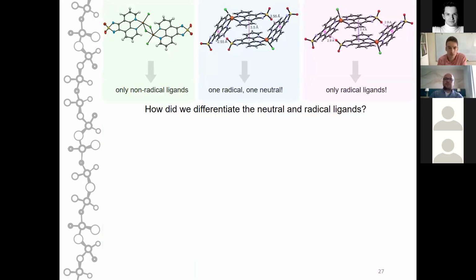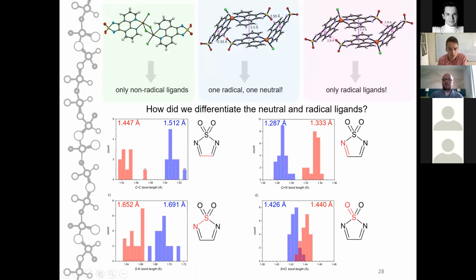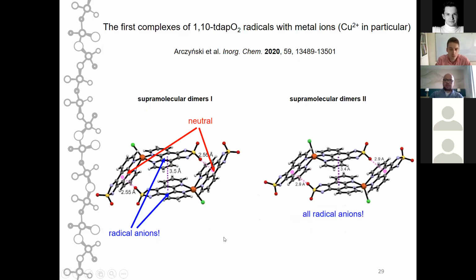So how did we differentiate that? You cannot do that from the magnetic measurements. It's not even possible from the EPR measurements. But it's very feasible when you analyze the respective bonds of the dioxothiadiazole moiety. So we did that in our recent paper. We have analyzed all accessible crystal structures of neutral and radical species involving dioxothiadiazoles, and you can see that when you move from the neutral species to the radical anion, for example, the CC bond actually shortens a lot. The same happens with the NS, and the opposite happens with the CN and SO bonds. So simply by analyzing the bond lengths in the crystal structure of your compound, you can actually assign the valence state of the molecule.